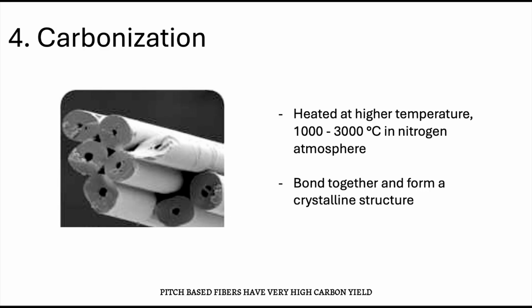Pitch-based fibers have very high carbon yield, about 80%, which is higher than PAN or rayon precursors. The carbonization step, however, follows the similar carbonization step used for PAN precursor. It is heated at higher temperature at around 1,000 to 3,000 degrees Celsius in nitrogen atmosphere. In addition, pitch molecules naturally align along the fiber axes during spinning, allowing high performance to be achieved during carbonization without applying large tensile stress.